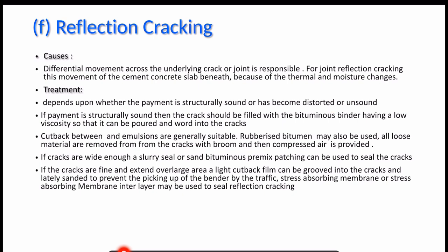In case the pavement is structurally sound, then we can fill these cracks with certain rubberized binder, or use fog seals, or we can seal the cracks using cutback emulsions. This will be cutback bitumen, using emulsions, rubberized bitumen, and likewise.